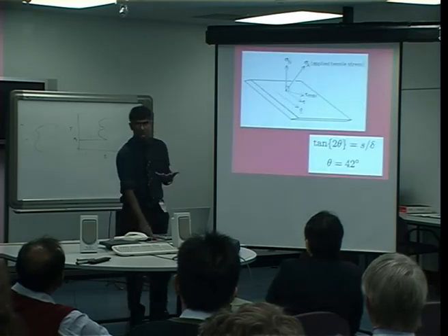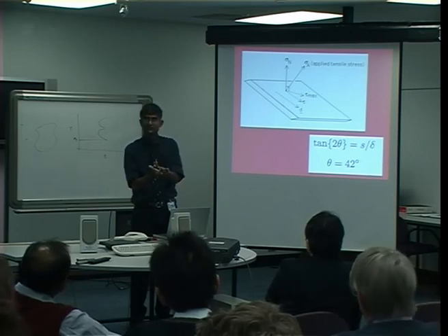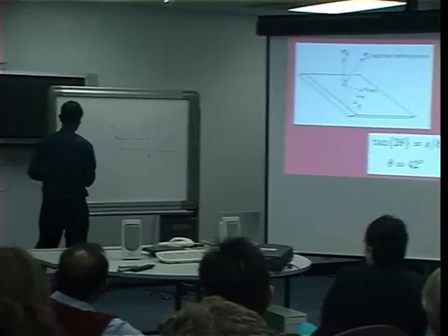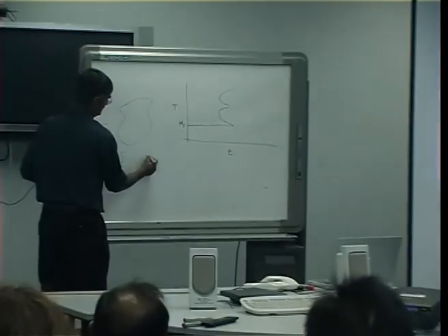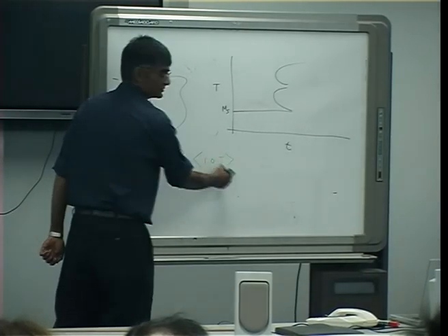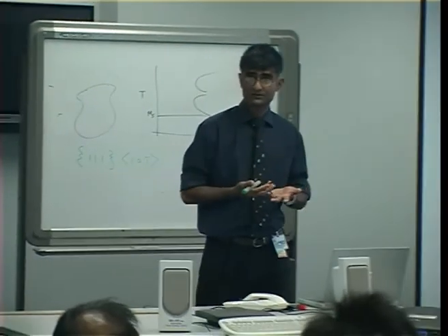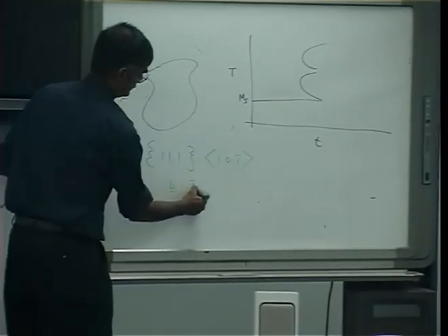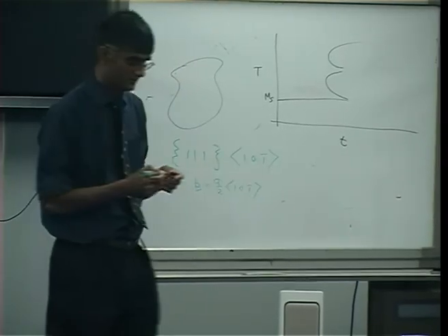So when we talk about slip, we have a slip system. That means it happens on a particular plane and in a particular direction. For example, in austenite, slip happens on the 111 planes and in the 101-bar directions. Right? Now, if we forget about the fact that martensite produces a crystal structure change, the further thing you define is the Burgers vector, a by 2 <101-bar>. So that's the magnitude of the displacement.